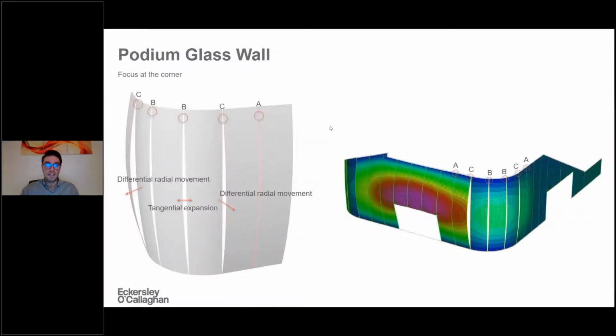One of the critical areas, probably the most interesting area of the project, was clearly the corner. This is because of the shape of the facade, where we have this rounded corner, and therefore the interfaces between flat and curved, and then again flat panels. Because of the geometry and the high load, we're talking about a Typhoon area as mentioned in the title, we got a peak of 3.5 kPa of wind load as a characteristic load here. So quite a high load, especially for the span of the facade, 15 meters.